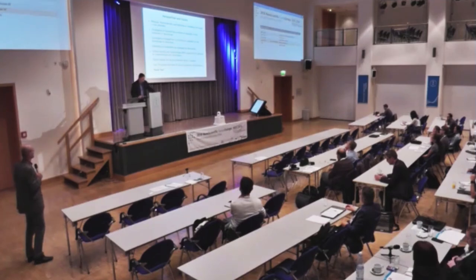Good question. We did this study basically to prove that 15 degrees C is enough to make that very big, whopping 150 degree change in contact angle measurement. What we did not do, and like you said would be interesting, is to look at the intermediate steps. If we hit it at 37, at 38, or look at it at 30, do we get intermediate wetting? My assumption is that the hydrogen bonding, driving the intramolecular interaction within the PNIPAM, has a big role to play. One of the tests that I've seen in the past is they actually use salts or other types of dopant molecules to mediate that intramolecular hydrogen bonding. But yes, that's a study that needs to be made, to look at the morphology or wetting behavior at various temperatures.